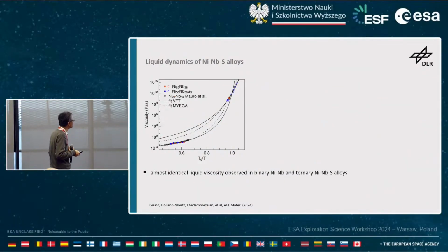Now I move to the sample which we intend to investigate on the space station. However, the situation is slightly different in this case. So we measured the viscosity of the melt in both regions. We measured the high temperature region. Some part of it has also been done on a parabolic flight facility. That's why there are only a few points here. I will show more, zooming in on the high temperature region, later on.